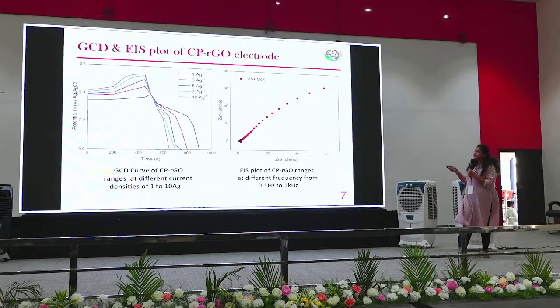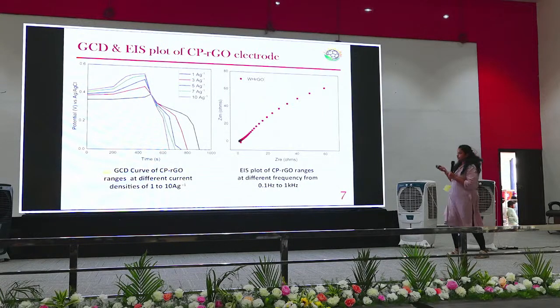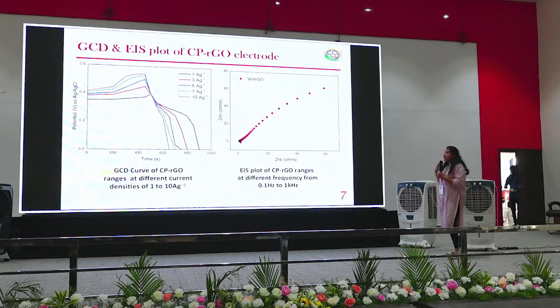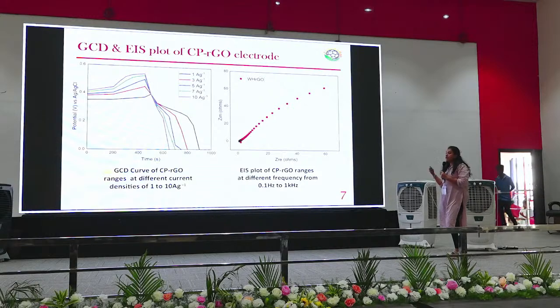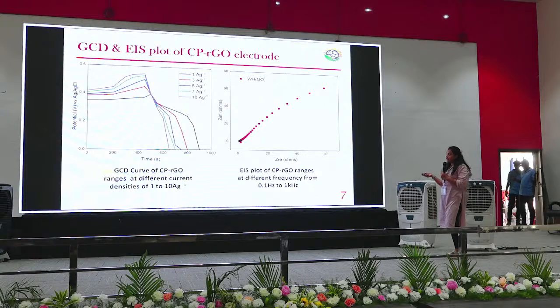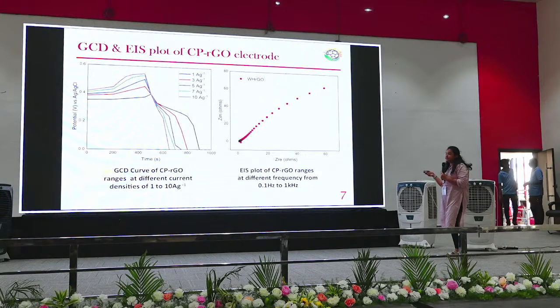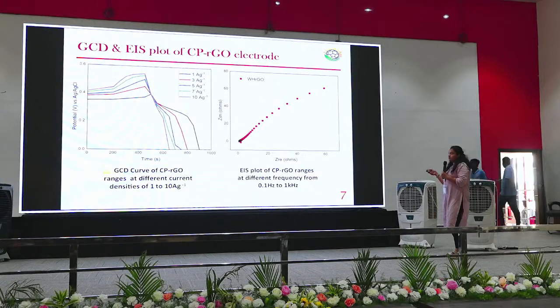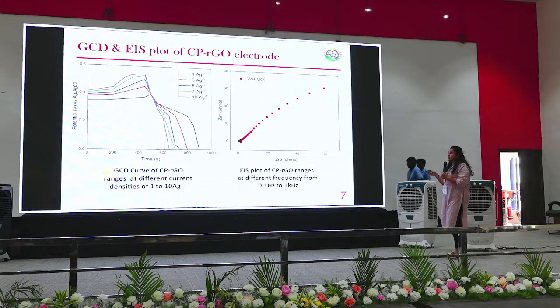And this is the charge discharge curve, where the active sites of the RGO allow the electrode and the electrolyte to interact, and the surface interface was very good, and hence we got this higher capacitance.